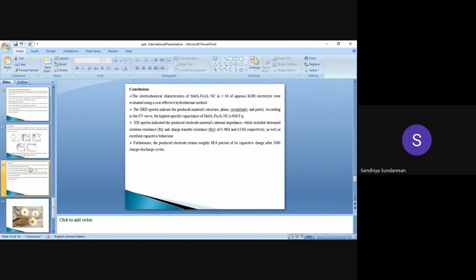The XRD spectra indicate the produced material's structure, phase, crystallinity, and purity. According to the CV curve, the highest specific capacitance of these composites is 908 farad per gram. The EIS spectra indicate the produced electrode material's internal impedance, which included decreased solution resistance and charge transfer resistance of 0.48 ohm and 0.01 ohm respectively, as well as excellent capacitive behavior. Further, the produced electrode retains roughly 88.8% capacitive charge after 3000 charge and discharge cycles.